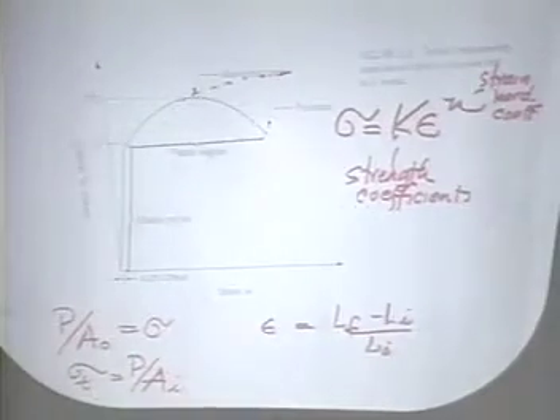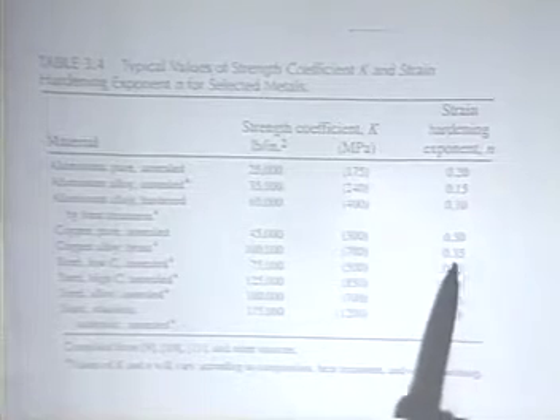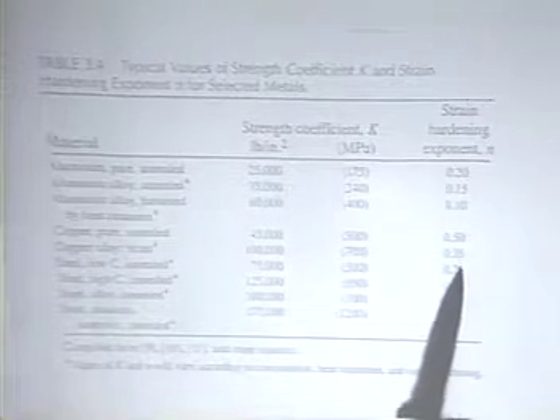Okay? So, just to give you an idea, here's pure aluminum at the top with a strength coefficient K of 25,000 psi, a strain hardening exponent of 0.20. We look at a typical low carbon steel, 3 times the strength coefficient. Okay? And also the strain hardening exponent is larger. So we know that steels are generally stronger than aluminum.